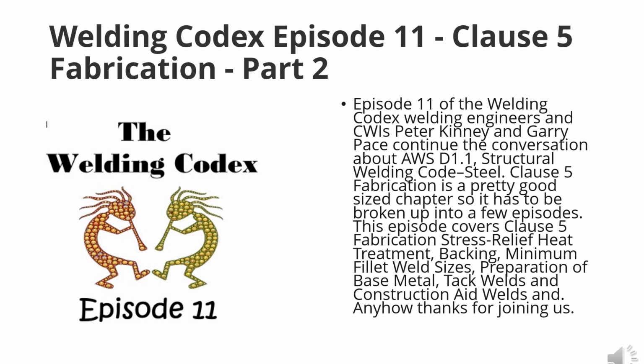Correct. And there's a subset when we get into these tack welds that are incorporated in the final product: when you deal with subarc, you get a pass on a couple items. And the reason you get the pass is subarc has the ability to penetrate very deeply, and it can consume or kind of chew up what it runs over, including tack welds. But as you said, we can't have cracked tacks.